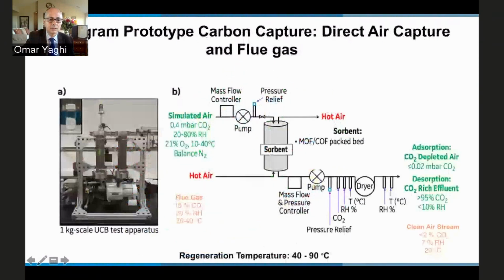for uptake. So we have set up a prototype where MOF 808 is the sorbent here, and we expose the material to a wave of gases. In this case, this is simulated air with 400 ppm CO2. And you see here that the outgoing air has only 0.02 millibar of CO2. So a significant reduction of the majority of the CO2 from air.